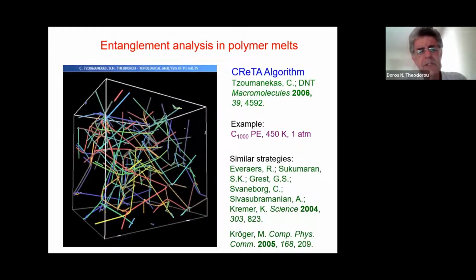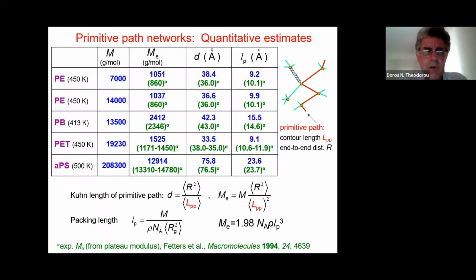So one can then go into this network of entanglements and analyze quantitatively. And here are some results for such an analysis for a variety of polymer melts: polyethylenes of 2 different molar masses, polybutadiene, polyethylene terephthalate, atactic polystyrene. And we have shown here the Kuhn length of a primitive path, or the entanglement tube diameter, as it is called, this D, which is nothing else than the mean squared end-to-end distance of the chains divided by the mean length of the primitive path, and also the molecular weight between entanglements, Me, which is again obtained from the molecular weight of the chain and these properties.